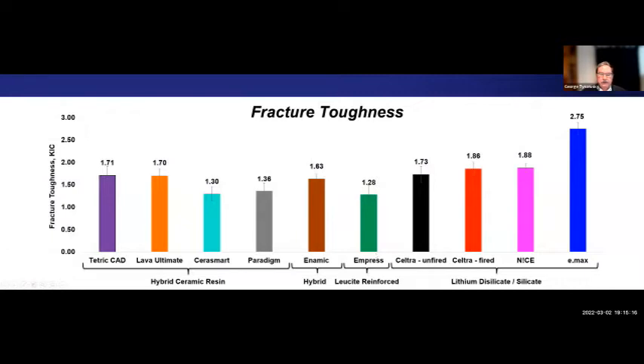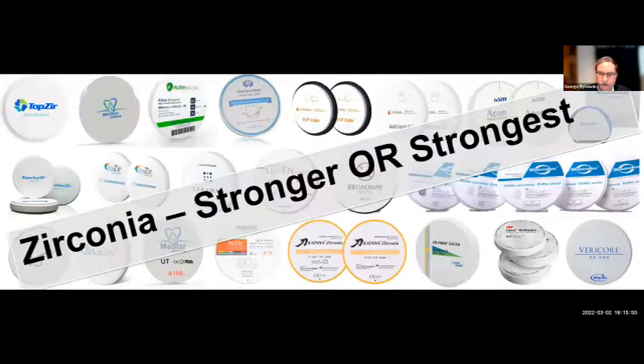So if we look at those comparisons again, the higher the fracture toughness, the better. Resin materials, which yield and bend, about 1.3 to 1.7. Enamic at about 1.6. Empress, a leucite reinforced ceramic, about 1.2. And then some of the lithium disilicate materials, Celtra Duo fired, at about 1.8, and then Emax at 2.75. So these are very important properties to remember. So again, from the Emax properties of lithium disilicate, we had about 500 to 600 on flexural strength and 2.75 on fracture toughness.